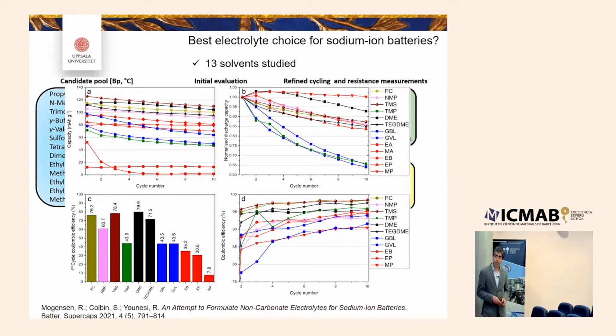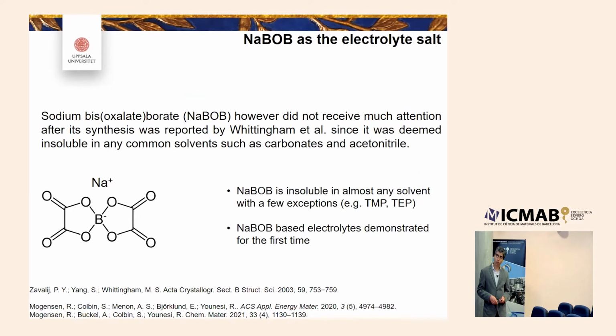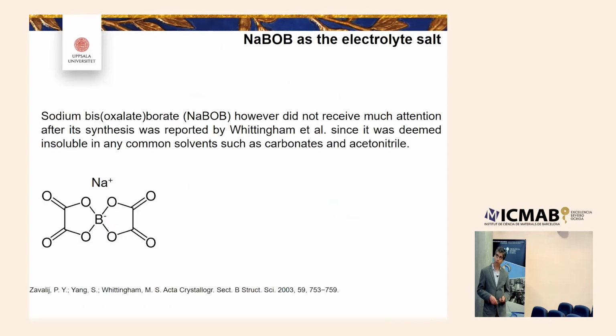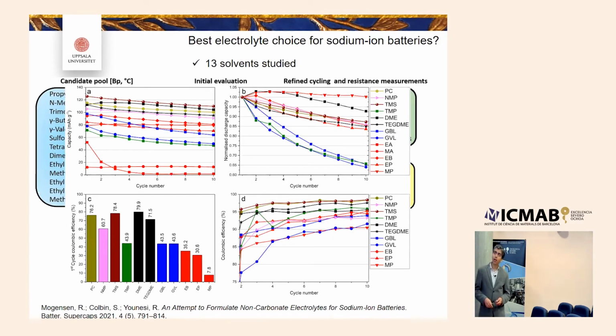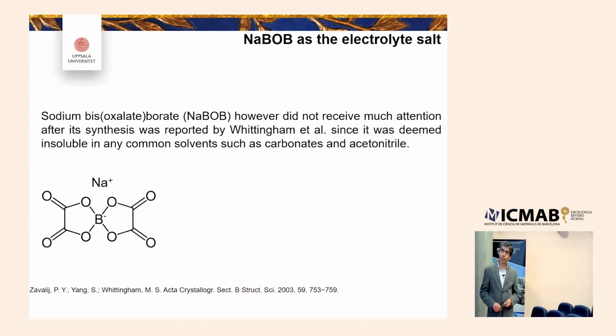The other step we took was, from this work where everything was based on PF6, we tried to move towards fluorine-free electrolytes. We found that if you look at fluorine-free electrolyte salts, there are only a few options. One is perchlorate, which there are still arguments around regarding whether it's safe or not.